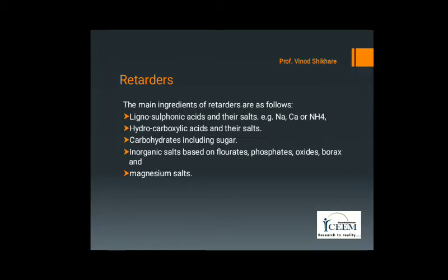Other admixtures which have been successfully used as retarding agents are lignosulfonic acid and their salts, hydroxylated carboxylic acid and their salts, which in addition to the retarding effect also reduce the quantity of water requirement for a given workability. This also increases 28 days compressive strength by 10 to 20%.